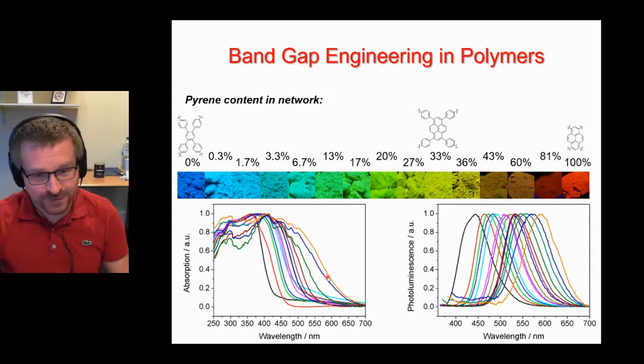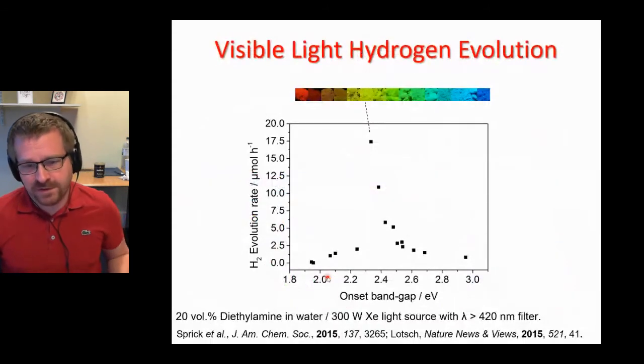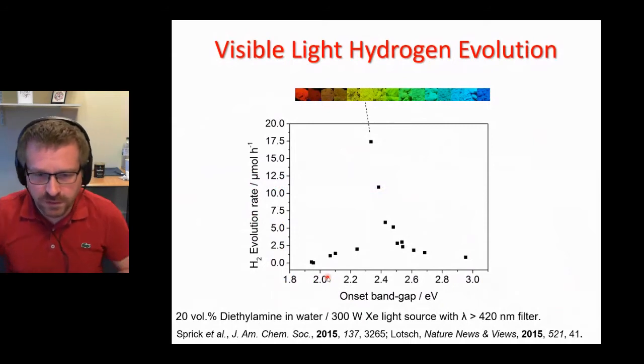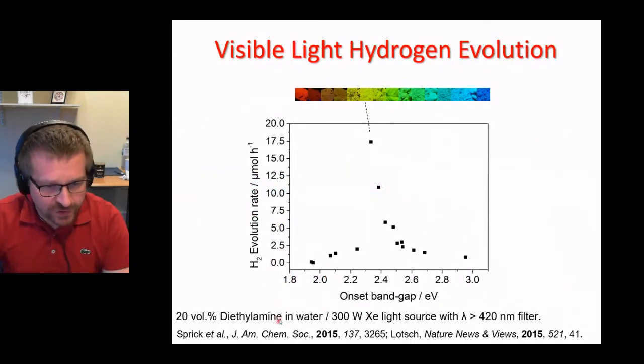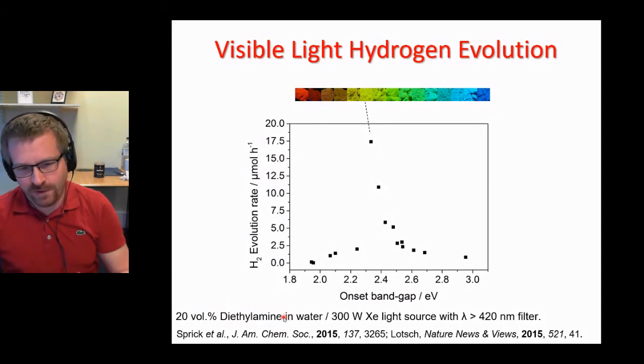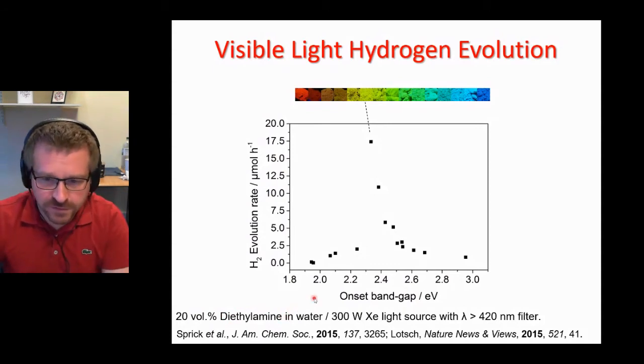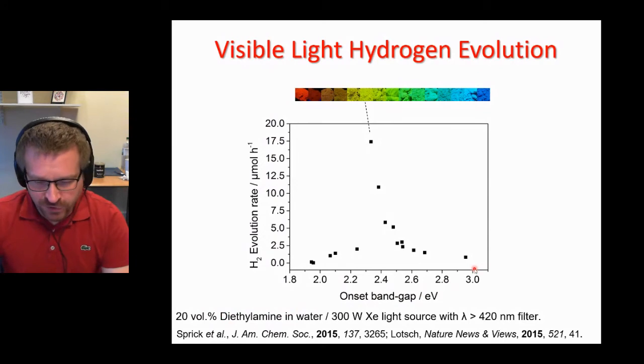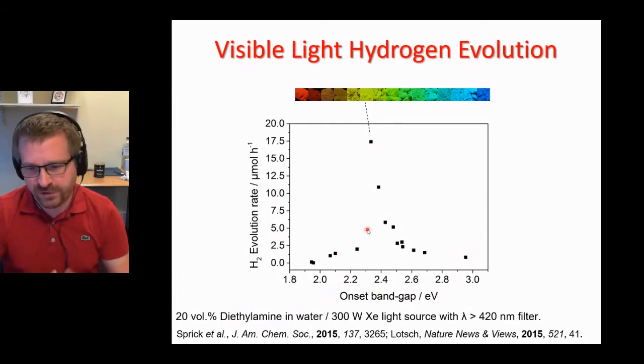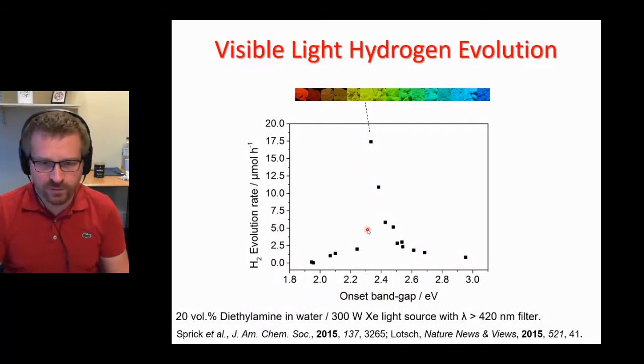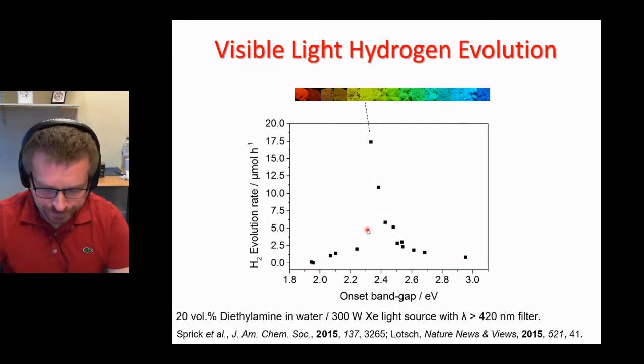And this was also our first go, really. And then these materials were tested for hydrogen production from water. I should say we used a scavenger, so we only do the half reaction where we produce hydrogen and oxidize this diethylamine instead of water. But it's a way forward here in exploring the performance of these systems. By using this tuning approach, we were able to find materials that are much more active. We went from this blue absorbed material here all the way up to this top material before we saw a drop off, and really shows the power of tuning, finding the best material in this case here.